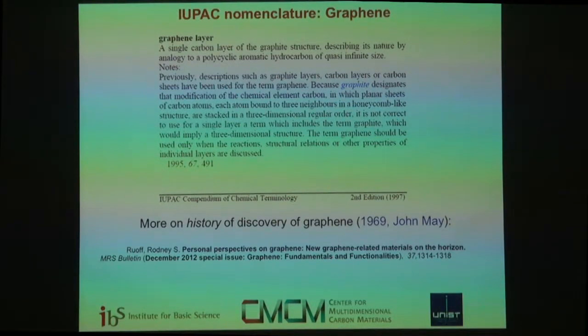energy electron diffraction, LEED, to look at the surface in a sense, to interrogate what was happening on the surface. So they had palladium-111, for example, and they saw the LEED spectrum change as a function of the dosing with acetylene. But they didn't assign the LEED patterns. They published 4 papers in different journals where they didn't actually state what they had, which is fine. That's good science. It moved the field forward. And John May was one of the world's experts on LEED, a theoretician, and he read their literature and published a short article in Surface Science explaining this is monolayer graphite. And then some of the LEED patterns were actually multi-layer graphene, we would call it now, that were either in the Bernal AB stack configuration or misoriented.